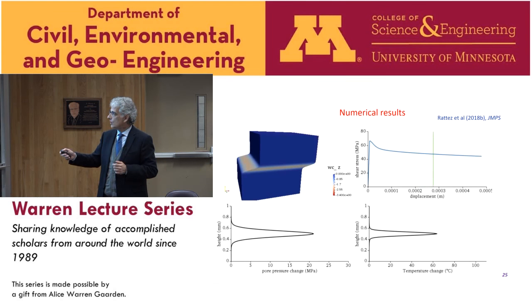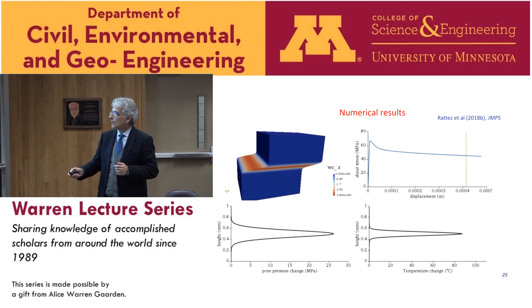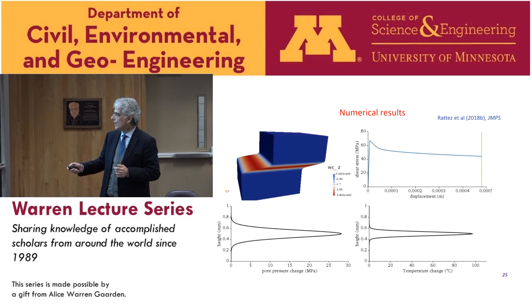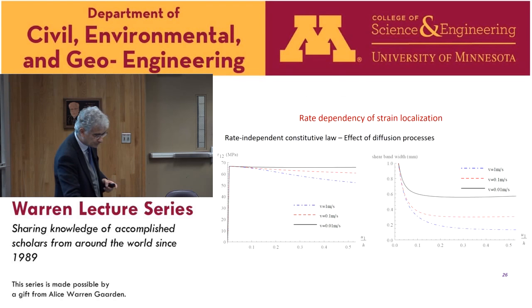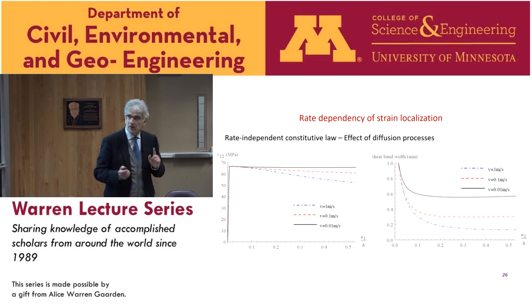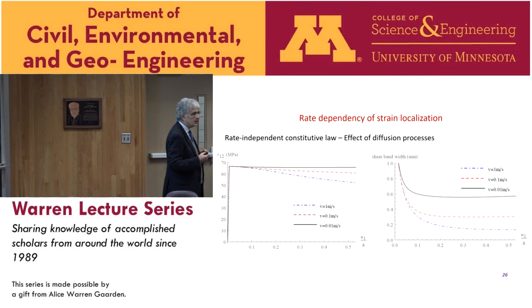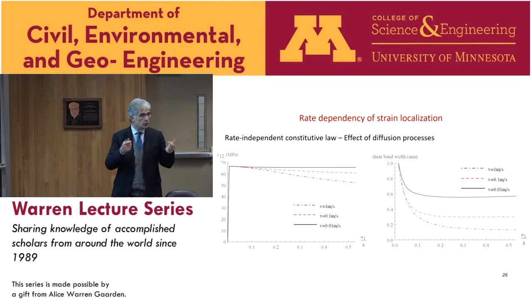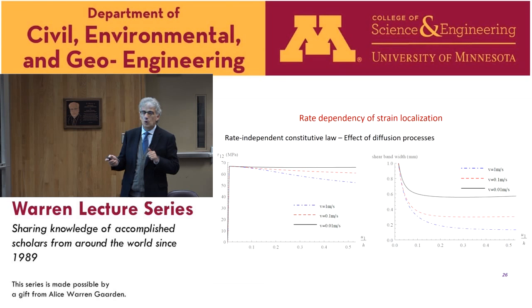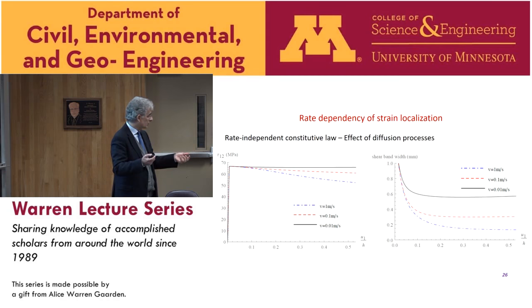So this is how the system softens in relation with the pore pressure increase inside the band and the temperature increase. All this is localized. Another interesting point is that we consider here a rate-independent constitutive law. As you know, in seismology, we commonly use what are called rate and state friction laws. So we generally introduce rate dependence of the friction coefficient, which we don't do here. We could, of course, but what I want to insist on is that even considering a rate-independent constitutive law, we have rate effects because of the diffusion process.